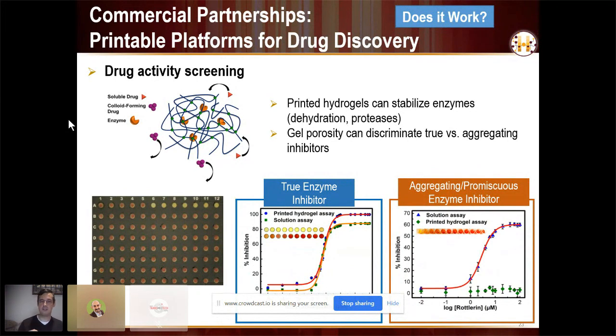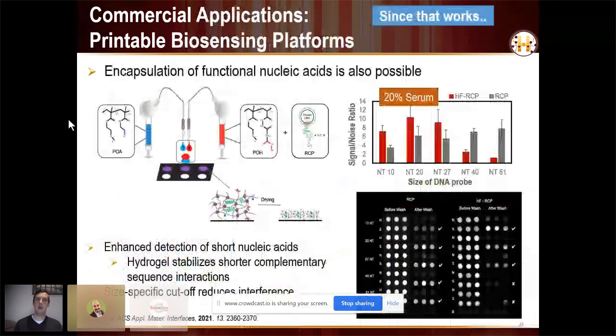But for the enzyme printed inside our gel, you can see that only the one that is actually a true inhibitor that can diffuse through our gel, bind to that hydrated enzyme inside the gel, gets the exact same IC50 value as we get in solution, whereas the one that aggregates and is thus too big to get into the pore structure of our gel and can no longer interact with the enzyme, we see no signal, no inhibition at all. So we think this has a lot of power to actually minimize the number of false leads that are pursued in the much more expensive second phase of drug discovery. And we're in talks with a drug company to perhaps try to implement this in some of those screening strategies.